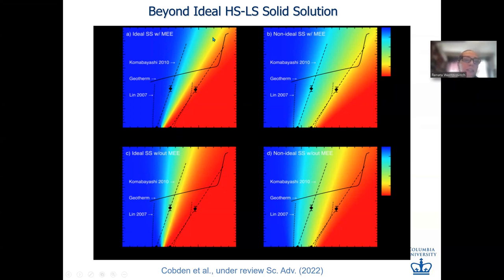Here is a different kind of change. So this is the previous rainbow. Here, the rainbow is more vertical. Why? It's the magnetic entropy. The electronic or magnetic entropy was calculated in the atomic limit, right? 2s+1. And so this is the maximum possible entropy. The electronic or magnetic entropy could be lower than that. So here there is no magnetic entropy at all. It's as if the ions have the minimum value for the magnetic entropy, 0. And that makes the rainbow more vertical.